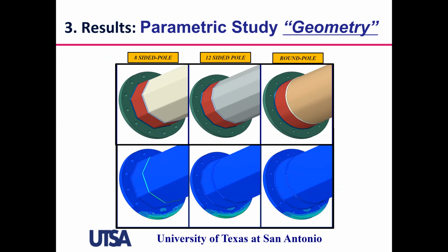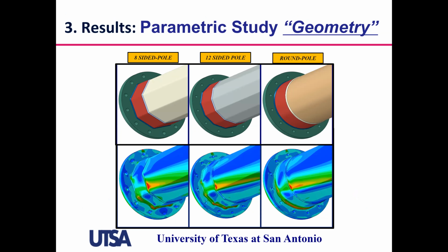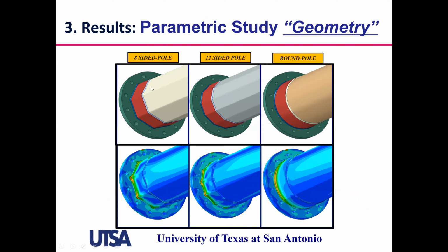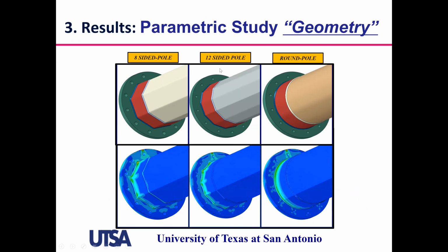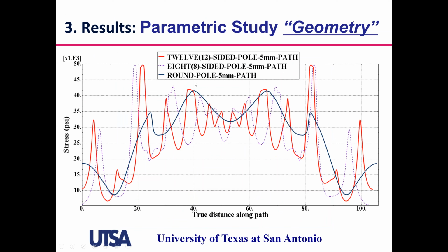Then we also studied the effect of the shape of the pole. So here you see we considered an 8-sided pole, a 12-sided pole, and a round pole. And we repeated the galvanizing simulations. And as you can see, the round poles have less stress demands during the simulation. And then the 12 and 8-sided poles have similar demands. So it seems that curved or round poles would contribute to lowering this crack formation phenomena.